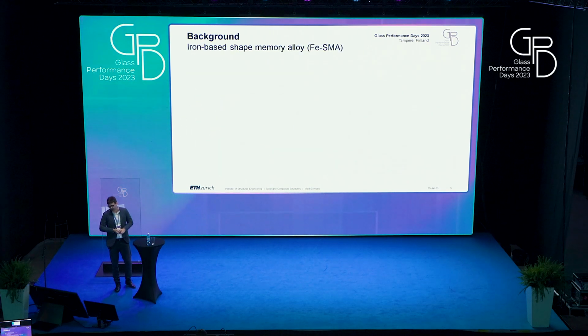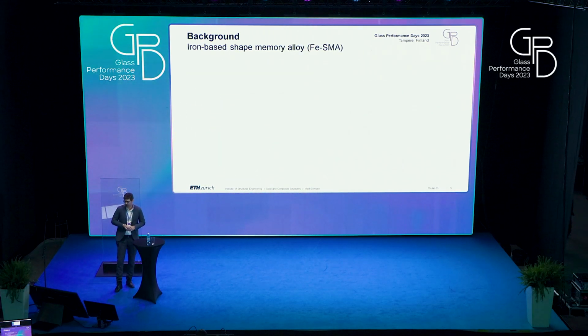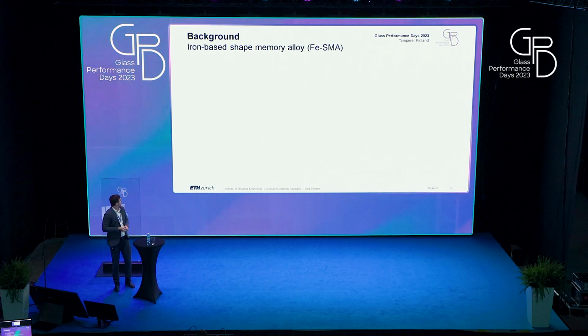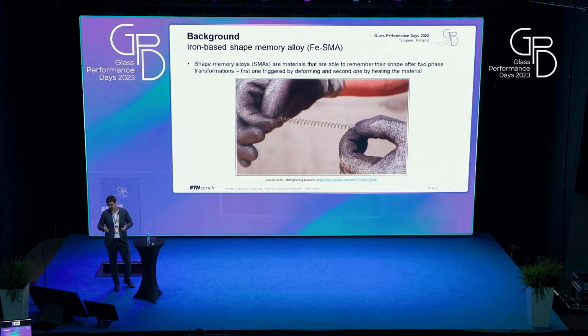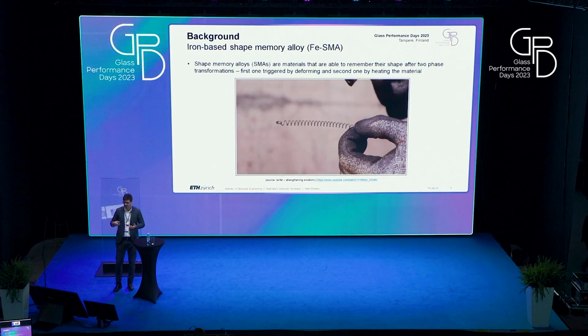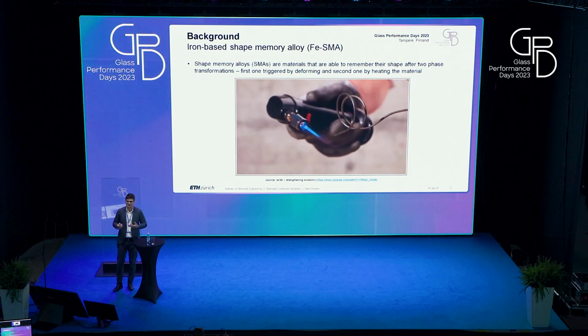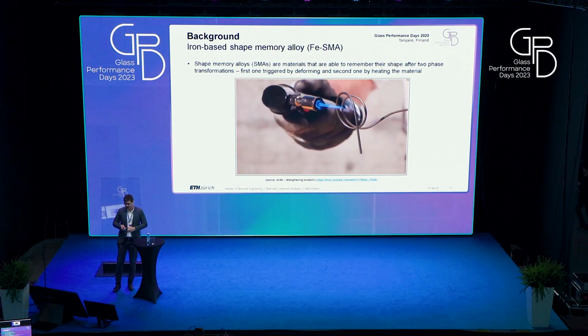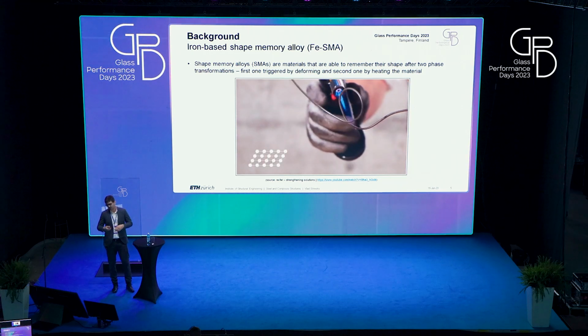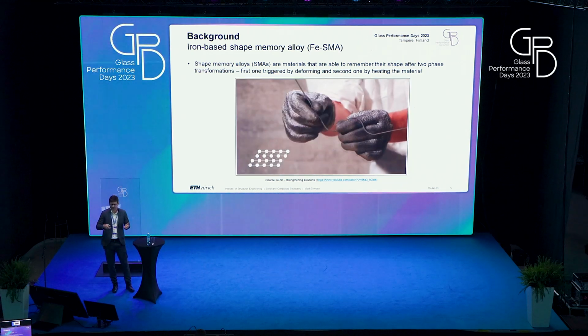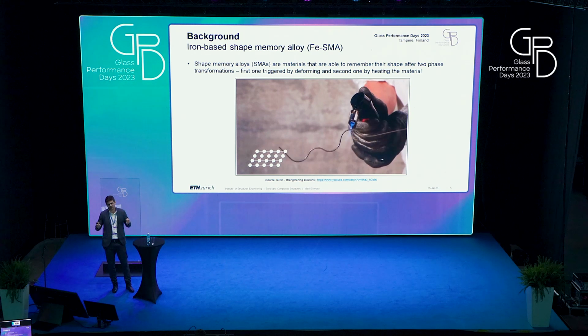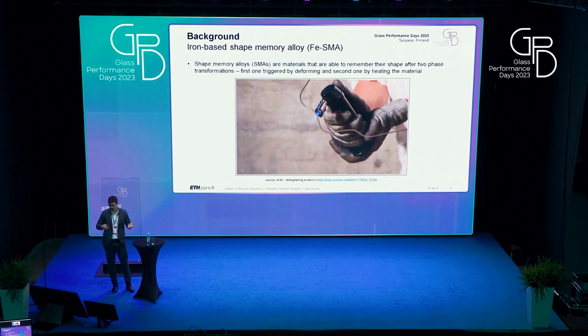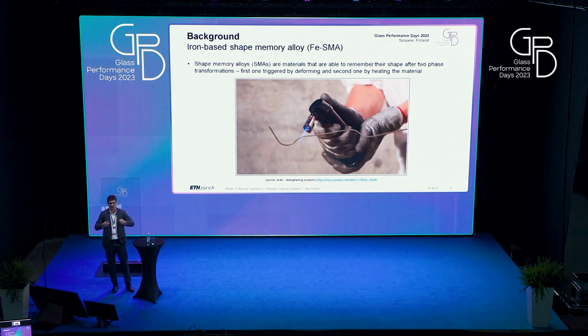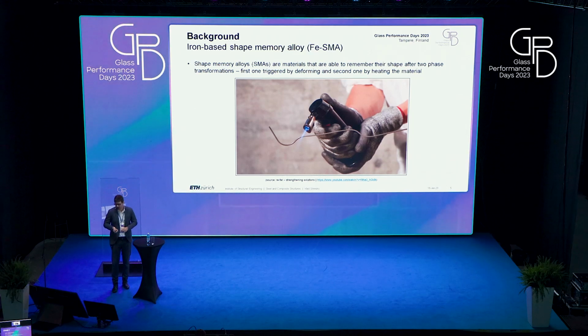So here comes into play the iron-based shape memory alloy that I mentioned. This kind of shape memory alloy is a material that is able to remember its shape after two-phase transformations. As you can see in this short video, for the iron-based shape memory alloy, the first transformation is triggered by deforming, and the second one by heating. So when you heat it, it wants to go back into the initial shape.